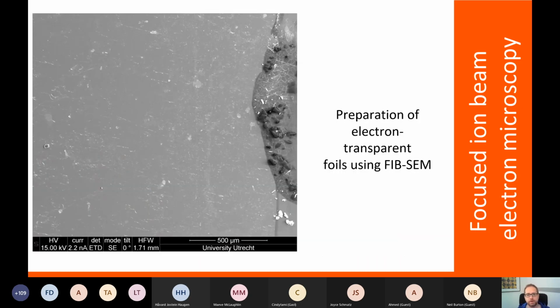Right, now that we know that we can manipulate materials using the focused ion beam, we can not only do tomography, but we can actually prepare samples, very site-specific, to go to a transmission electron microscope. Because, as you probably noticed in the first picture, in a TEM, we have to go through the sample. And this is only possible when samples are really thin, so typically around 100 nanometers to become electron transparent. And we need to make these samples. There's various methods, but the state-of-the-art method that also allows us to be extremely specific, I want to have my sample right here across an interface and not 5 micrometers to the right, is in the focused ion beam scanning electron microscope.